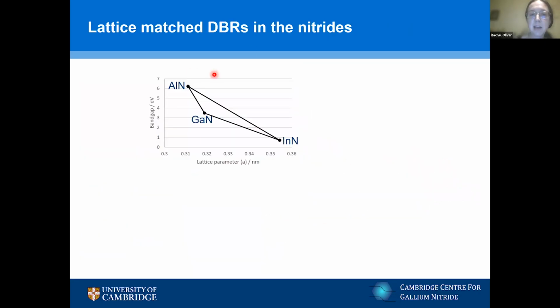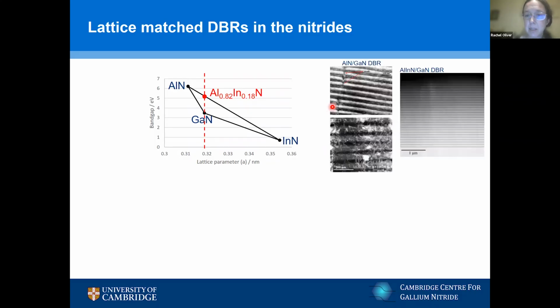So this is that region of the diagram, which is band gap versus lattice parameter, but zoomed in a bit. We can't lattice match gallium nitride and aluminium nitride. They definitely have different lattice parameters, but we can lattice match gallium nitride to aluminium indium nitride at 18% indium. And we can see what the impact is here of that lattice matching. This is a gallium nitride, aluminium nitride DBR. The aluminium nitride is in tension on the gallium nitride, and it tends to crack. That causes imperfections and changes in the thickness of the layers, which reduces the reflectivity. Also, the strain leads to a plethora of extra defects. The aluminium indium nitride, though, which is lattice matched, we have rather beautiful, perfect layers over a really, really large stack.